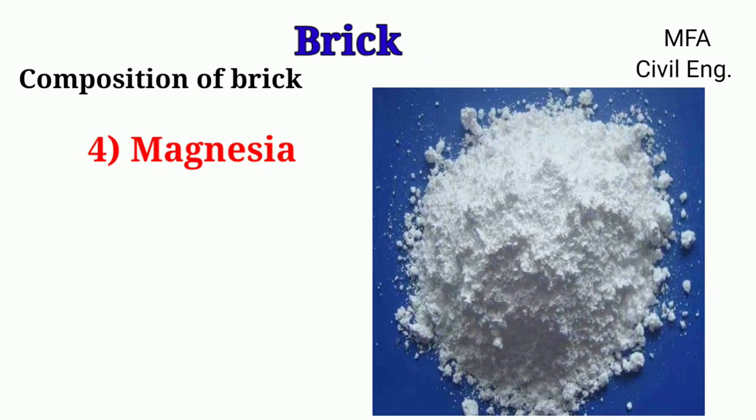Magnesia also acts as a flux during burning. A very small amount of magnesia gives a yellow tint to the brick and also decreases shrinkage. Excess magnesia, that is more than one percent, causes bricks to decay.